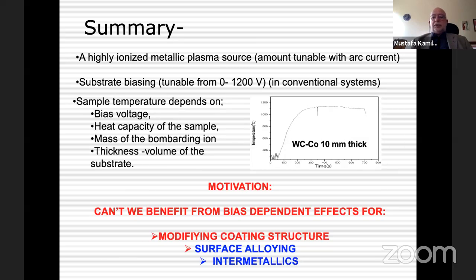We can tune it between 0 to 1,200 volts in conventional systems. So in this manner, we can have sample temperature depending on bias voltage, heat capacity, mass of the bombarding ions, thickness to volume ratio of the substrate, etc. So our main aim was, can we benefit from bias-dependent effects by modifying the coating structure and surface alloy?